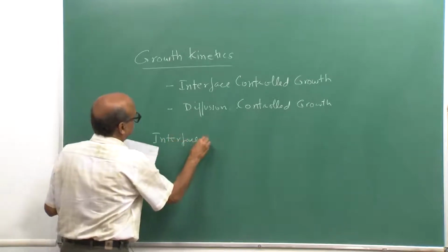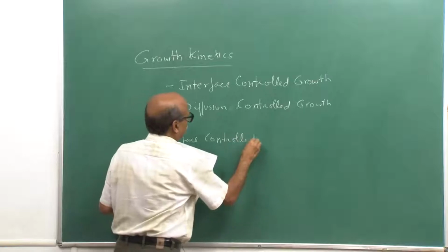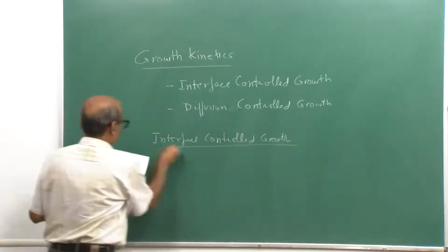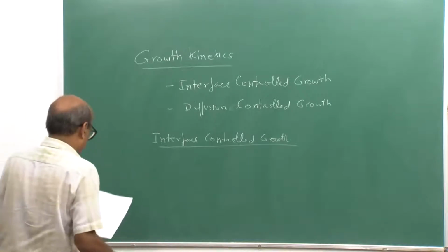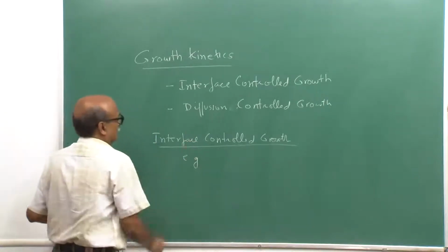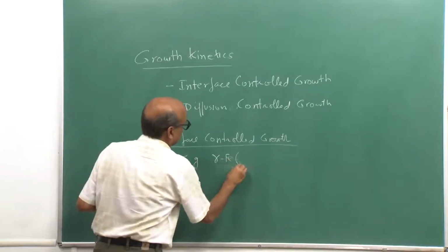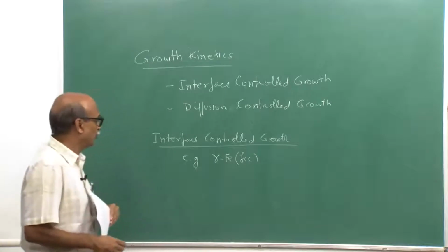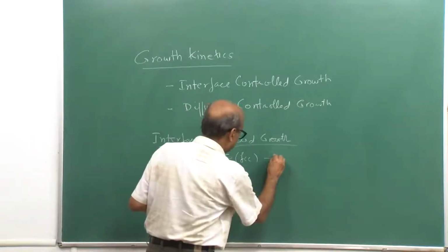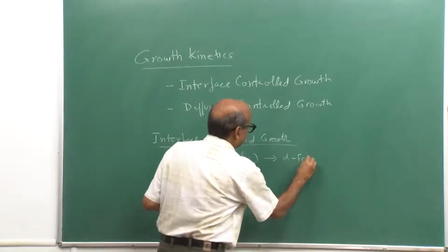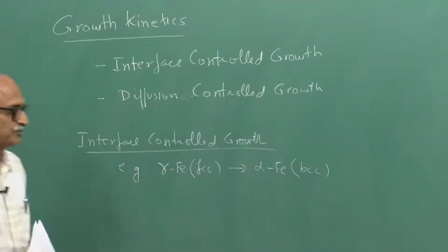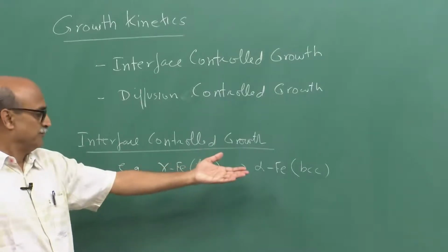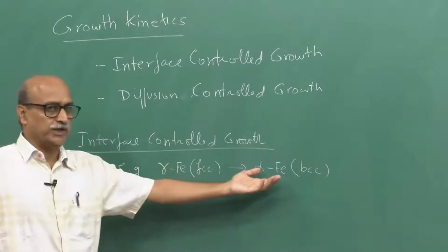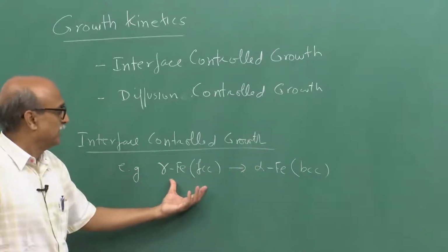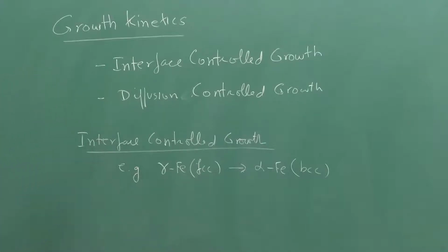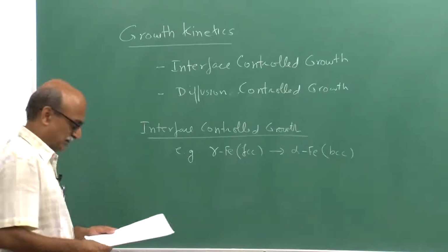So, in interface controlled growth, for example, gamma iron, which is a face centered cubic structure, on cooling below 910 degrees centigrade transforms to alpha iron, which is a body centered cubic structure. So, this is a single component system in which a growth of an alpha nuclei that forms in gamma iron then grows via the mechanism of interface control growth that we had seen in the last lecture.